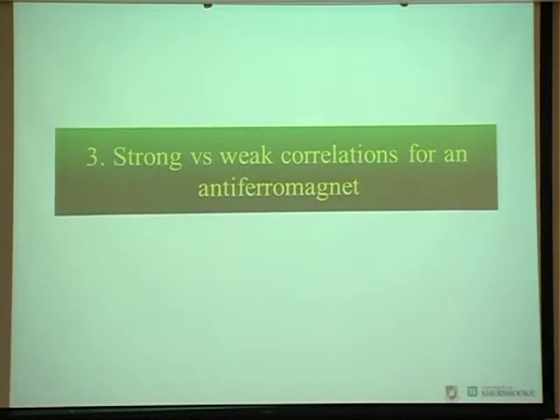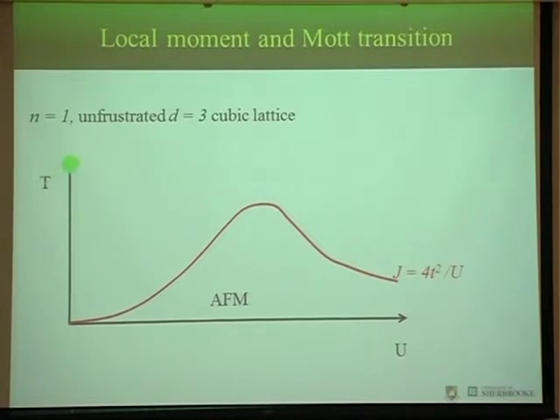Another way to look at weak and strong correlations for the antiferromagnet is just to draw this phase diagram for a three-dimensional cubic lattice, of temperature as a function of U. The antiferromagnetism exists all over this region below the red line. So this is a single phase, whether U is small or large. Nevertheless, properties are quite different. I will talk about this line in a minute. If I come from this way, I come from a metal towards the antiferromagnet, and the physics is that of nesting, Stoner antiferromagnetism. On this side, I come from localized moments, and the physics of ordering here is the physics of the Heisenberg model.